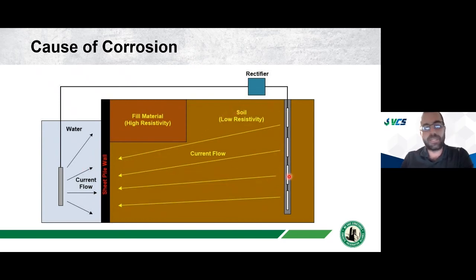But current always takes the path of least resistance. So in the native soil that had a higher moisture content and lower resistance, that's where the majority of the current was flowing. But in this area of high resistivity fill, they were getting significantly less current flowing up there. And so we were asked to do an assessment of this and identify what the issue was. And that ended up being that the design of the CP system wasn't taking into consideration this high resistivity backfill material in one area up at the high point of the wall. So they were obviously getting some corrosion up here because they weren't getting proper protection.